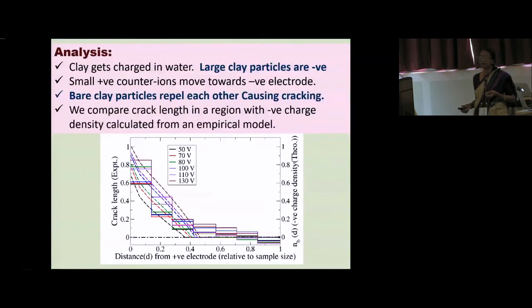To explain this, we argue in this way that when laponite or any clay is in an aqueous environment, usually it gets charged. The positive ions leave the large clay particles, leaving the bare laponite disk with a net negative charge. And the small counter ions are free to move. So in the electric field, the counter ions will move towards the negative electrode. And the bare clay particles which are left repel each other, and that creates the cracks at the positive electrode. That is what we are suggesting.